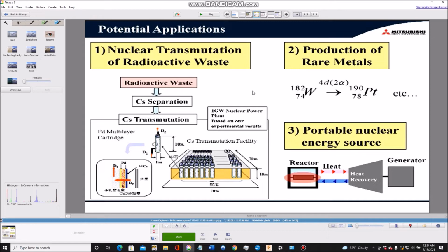So the reason we're talking about transmutation and not just heat production is because the heat production results are not as promising, and the main reason for that is that the actual heat, the excess heat produced, is quite minimal. Most reactions have produced excess heat around a ratio of about 1.10, so you get 10% extra heat. Mizuno has been able to produce around 2 times excess heat, but you're talking low-grade heat. This is pretty low-grade heat, and so you'd have to use maybe a Stirling engine or thermoelectric generator that has pretty low efficiency, and so the actual net heat output would be quite small.